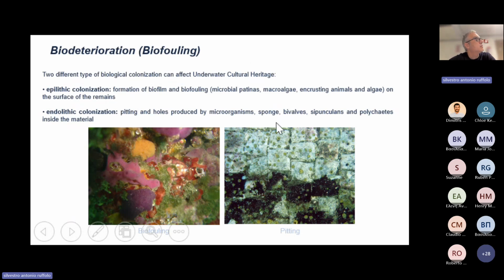So when I deal with so-called biodeterioration or biofouling, another term to describe this phenomenon, I have two different types of biological colonization. These two types are very different from a conservation point of view. I can have an epilithic colonization, which is a biofilm that remains on the surface. And the second type is the endolithic colonization. In this case, I can have a much more complex and dangerous phenomenon: pitting and holes produced by microorganisms that can get into the stone materials.